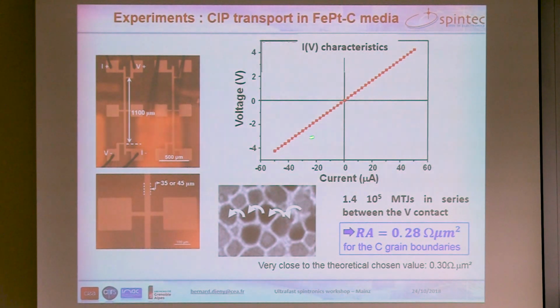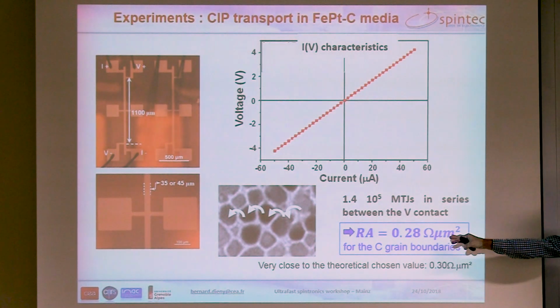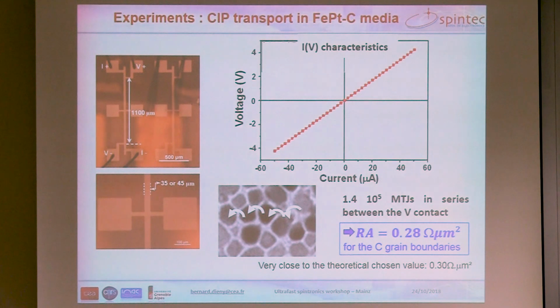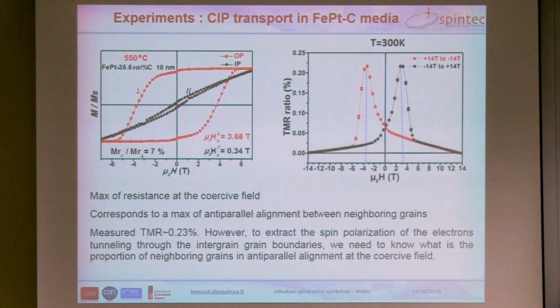So from the measurement of the slope here, we can determine the resistance and the resistance-area product of these grain boundaries, and we got 0.28 ohm micron square. So it's not too different from the 0.30 ohm micron square that we had with the theoretical parameters that we determined. So besides this value, we want also to know the polarization of the electrons. So for this, we measured the magnetoresistance of the media.